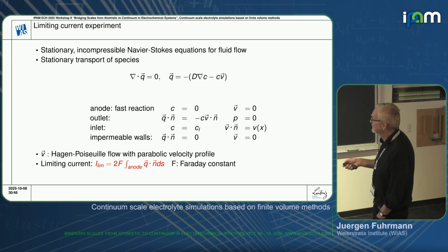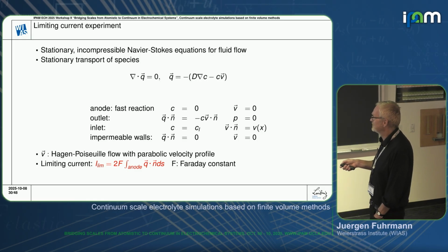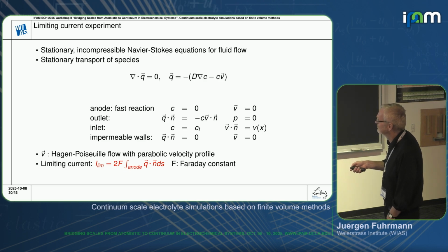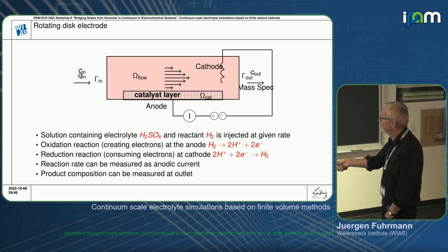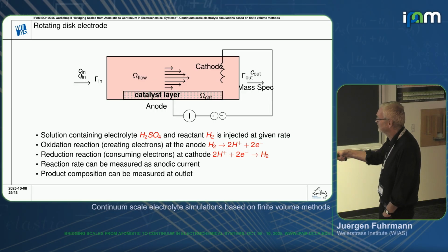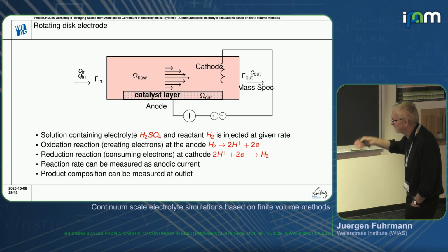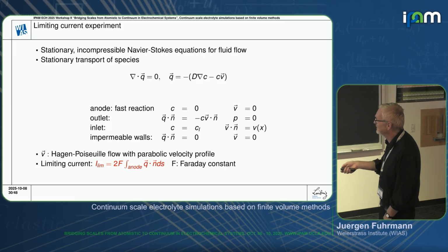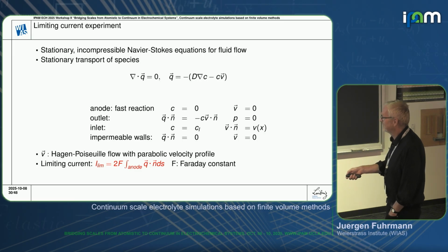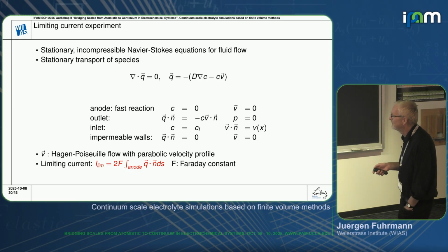And here we use the convective diffusion equation, in this case for the hydrogen species, in order to describe the transport. And the particular thing is that we assume that we have a zero concentration at this catalyst layer, which means that the electrostatic potential is chosen in such a way that the reaction is fast. So we get the limiting current, which we then can measure just as the flux of the species through this boundary condition at the anode.